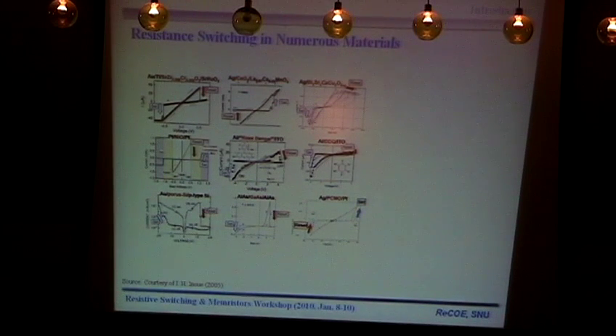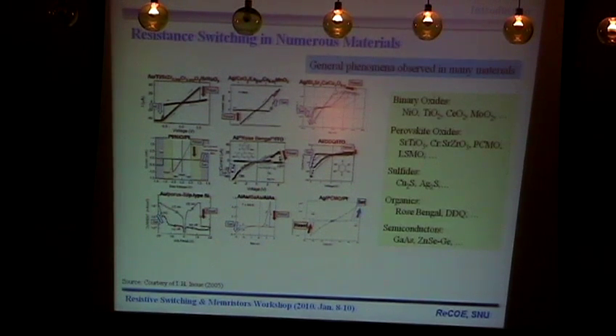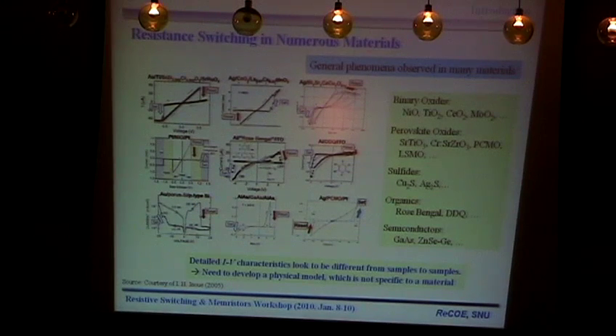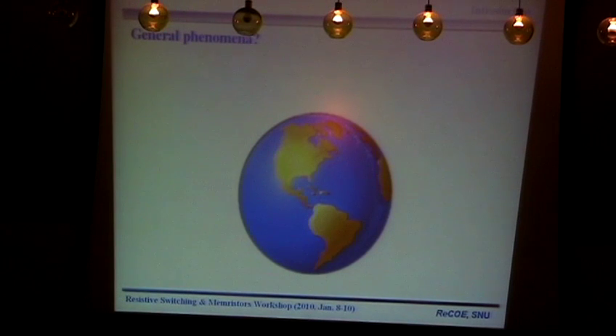In addition, this is the collection of the IV characteristics actually done by Dr. Inoue. And this is actually the material reported after the year 2000. Then if you look at this material, you can clearly see that this resistance switching has been observed in binary oxide, perovskite, sulfide, organic, semiconductors, and so on. So this is a general phenomenon observed in many material systems, not just in oxide. Also, if you look at the details of the IV characteristics, they look quite different from sample to sample. So this all indicates that we need to develop a physical model which is not specific to material systems, something like oxide. So what is the general phenomenon of general physics?